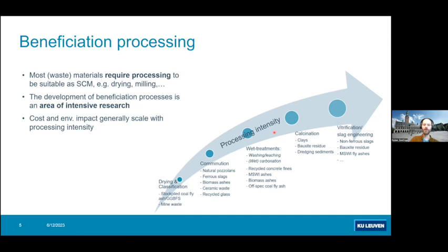Wet processing, washing, leaching in some cases, has been seen as quite effective in improving properties or resolving issues with some SCMs. Carbonation, obviously, mineral carbonation is something which is really in the spotlight today for recycled concrete fines, for instance, where the CSH, or the non-carbonated calcium, is carbonated and produces both a material which is reactive and can store CO2. Moving up the ladder, we go into even more energy-intensive processing. There are calcination treatments and even vitrification. Calcination of clays, obviously, but also vitrification of certain waste streams can give you a slag with interesting properties. So this is a kind of subdivision of the processes that we see being developed today.